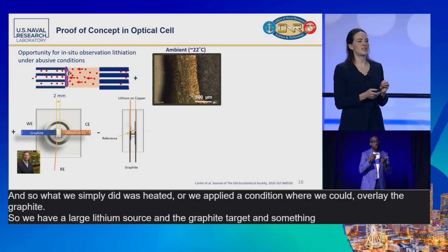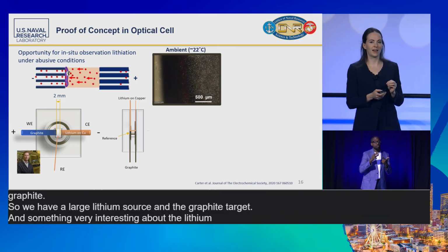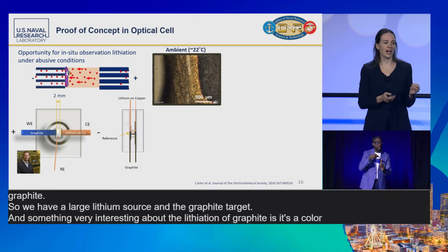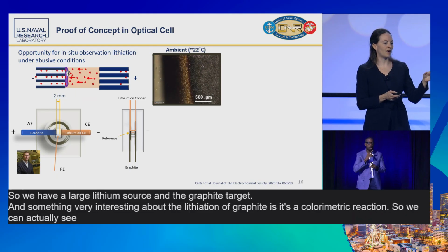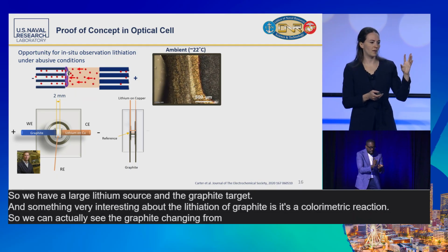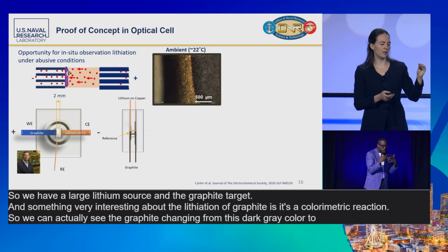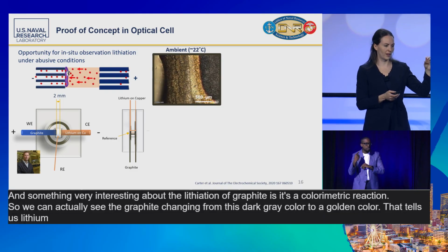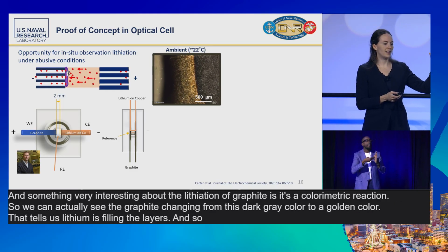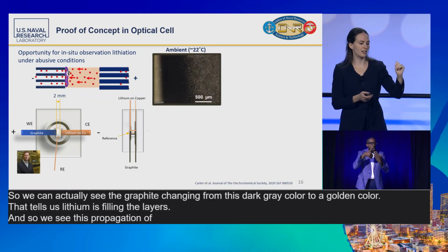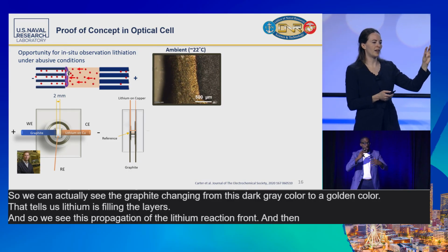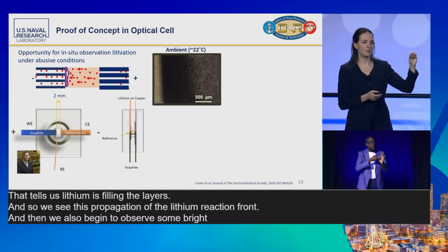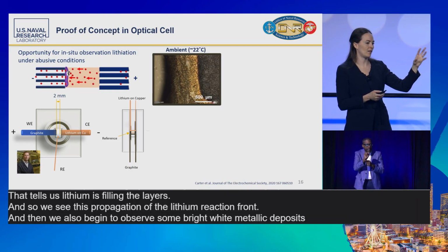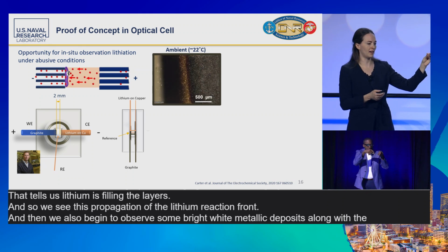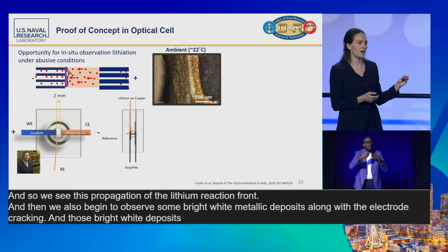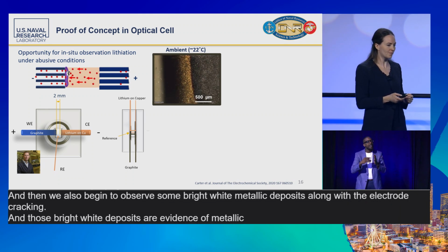And something very interesting about the lithiation of graphite is it's a colorimetric reaction. So we can actually see the graphite changing from this dark gray color to a golden color that tells us lithium is filling the layers. And so we see this propagation of the lithium reaction front, and then we also begin to observe some bright white metallic deposits along with the electrode cracking. And those bright white deposits are evidence of metallic lithium plating.